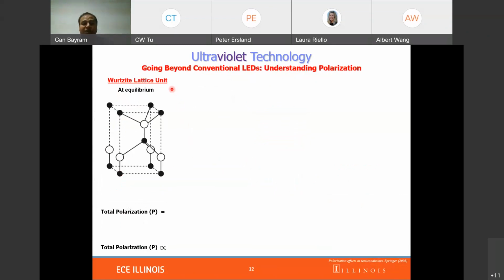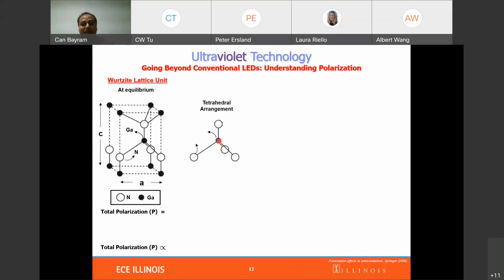Now, how can we go beyond these conventional LEDs? Here is the lattice structure of an LED. Basically, it's a Wurtzite structure with gallium and nitrogen connected. A here is the lattice parameter of the base, and C is the lattice parameter in this direction. Now, these gallium and nitrogen atoms are connected in a tetrahedral arrangement. Because of their different properties, they have a spontaneous polarization due to electronegativity. And overall, because of the angle and the bonds, there is an inherent spontaneous polarization field that exists in the material, and this depends on the composition, meaning the aluminum gallium content.